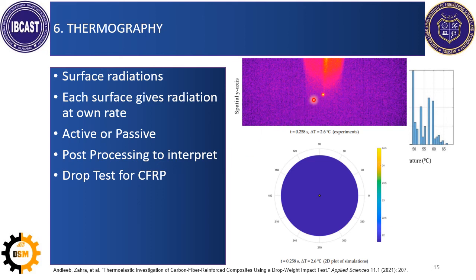This was passive thermography, and we did the same with the help of a numerical model, and we saw that there was a 2.6 degree rise in temperature. It was a very fast rise in temperature, and it vanished away very quickly. So you need high resolution and high speed thermal cameras in order to detect such changes. But with the modern technology available, these methods are very effective. They are non-contact, and they can keep a very good record of all the changes happening in your CFRP laminates.